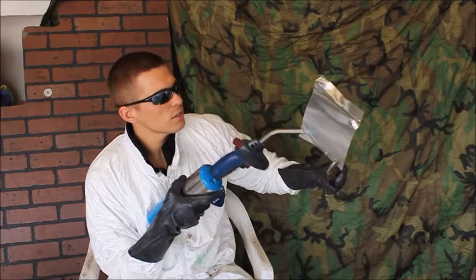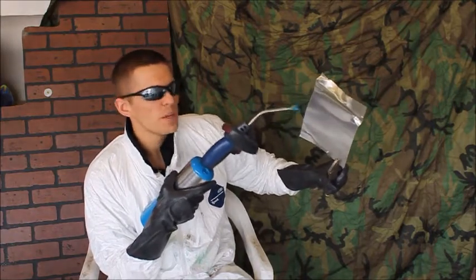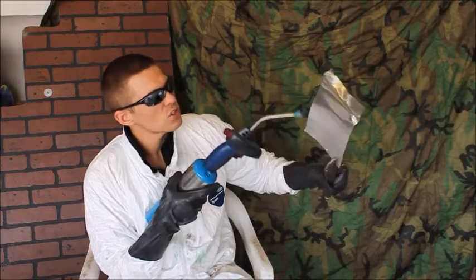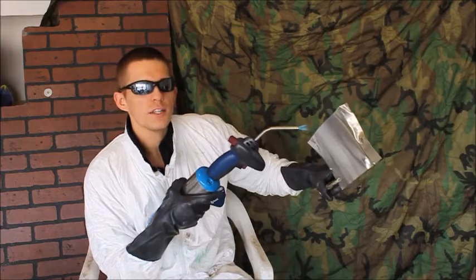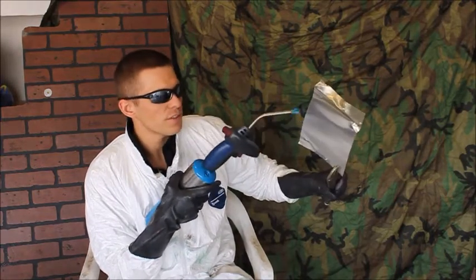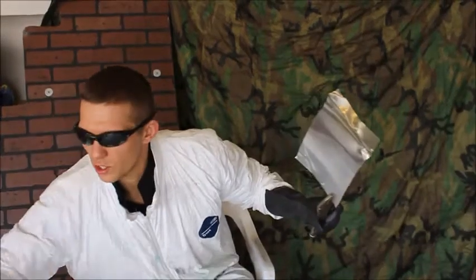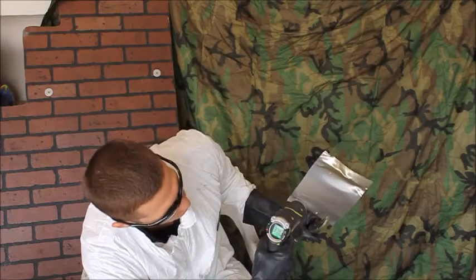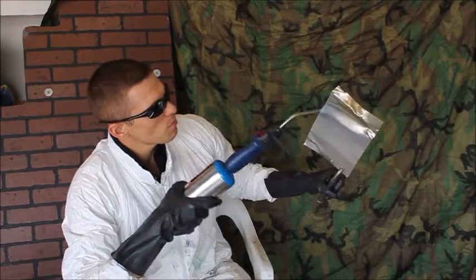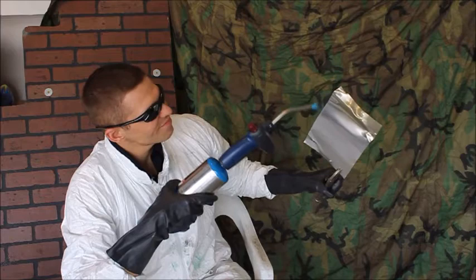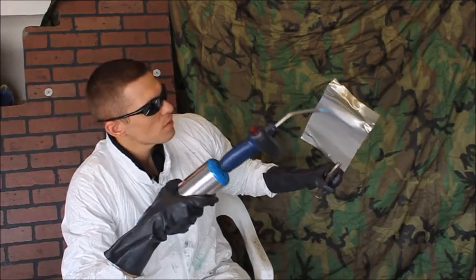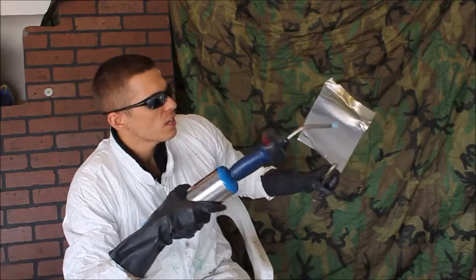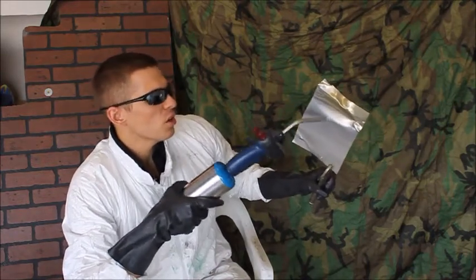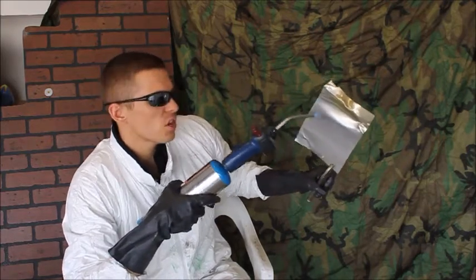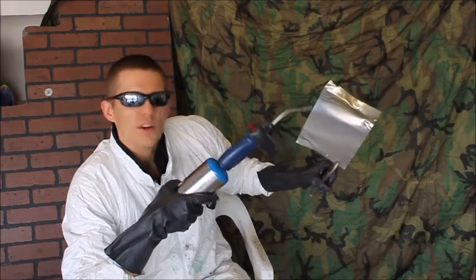Most paints or coatings by this stage will already bubble or burn away. Yet this is holding strong, holding a good shine, and not really noticing anything. So let's go ahead and temperature test it. We are at 380 degrees Fahrenheit. Let's go a little bit more. At this stage, the metal itself is turning yellow. It's actually tarnishing because of the heat. So the metal underneath is actually discoloring because of the heat before the coating itself has been affected. This right here is the power of nanotechnology, people.